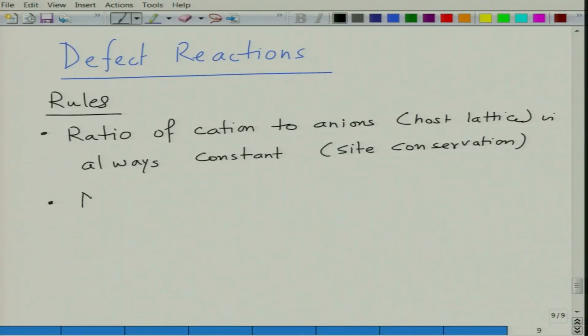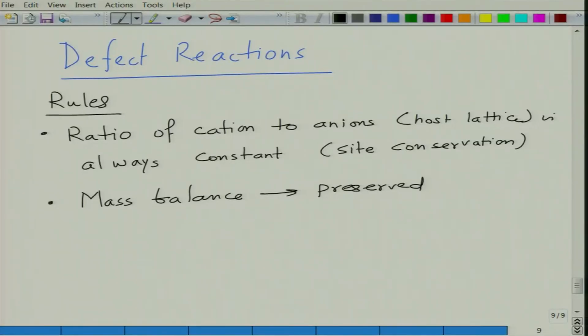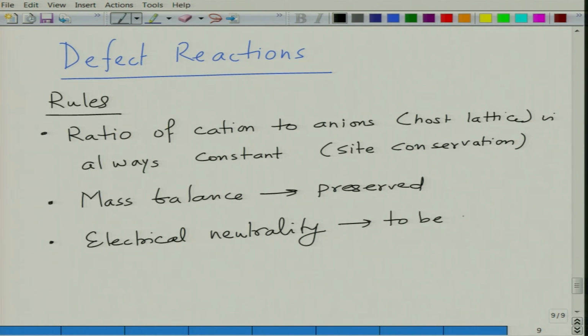Then mass balance. Mass balance has to be preserved. Whatever goes in has to be accommodated and accounted for. You cannot have disturbance or inequality in the masses. You have to account for each and everything that comes in and goes out. And then we have electrical neutrality, which in the end has to be preserved. The solid has to be always electrically neutral. You cannot have an imbalance of charges. All the positive charges have to satisfy all the negative charges, so that the solid is always electrically neutral.